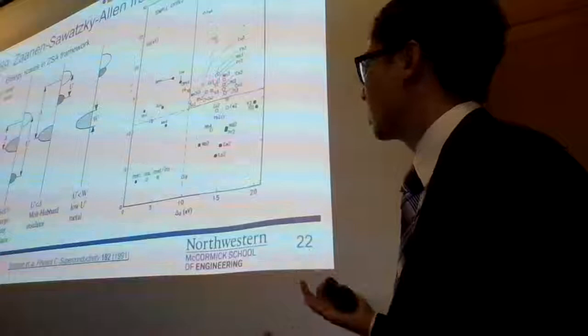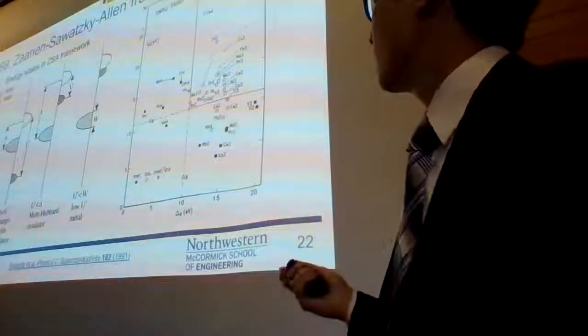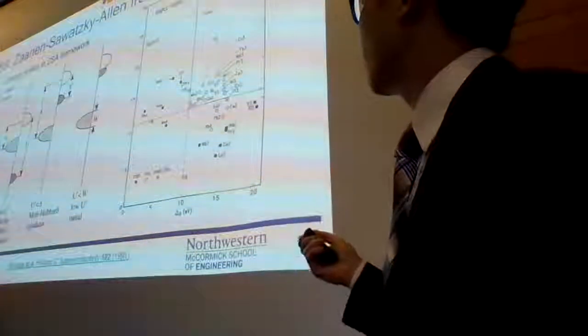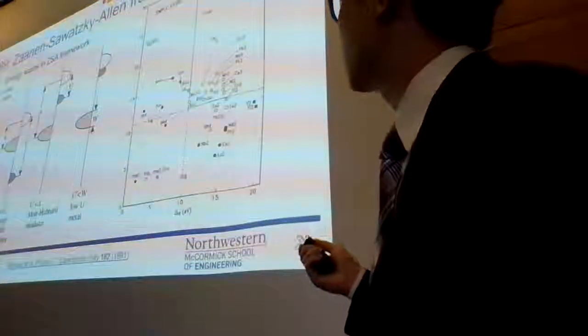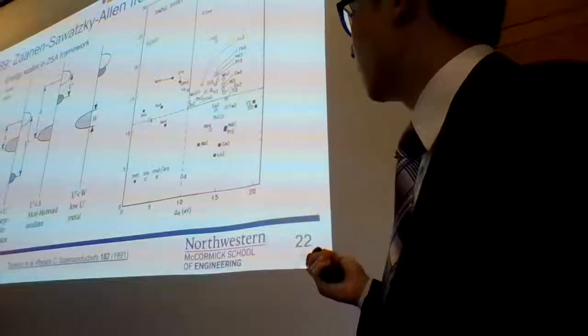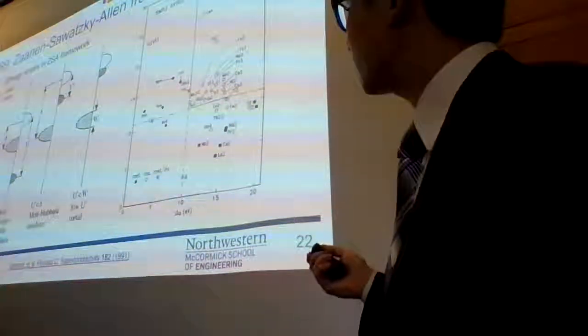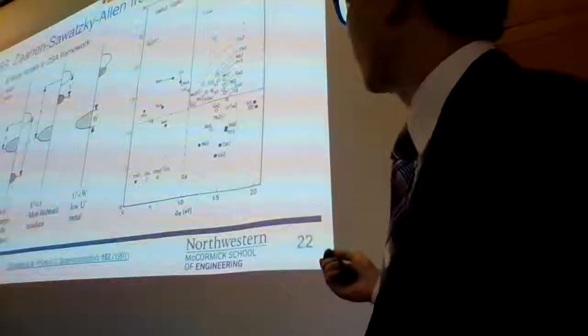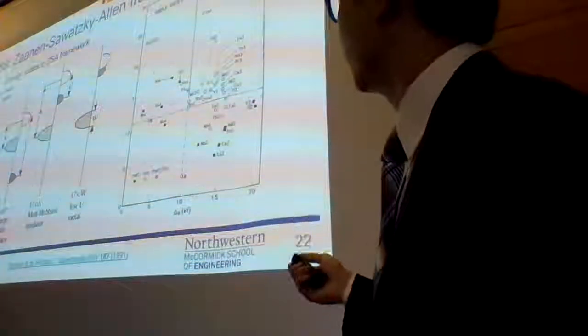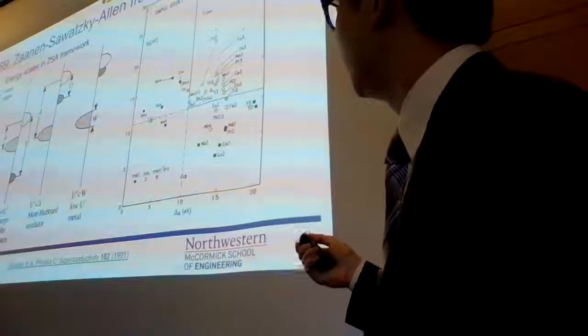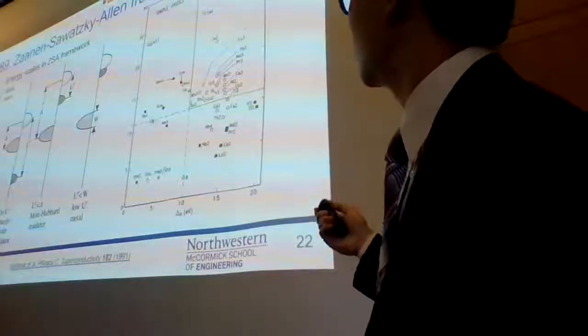It requires the structure of the material, which is kind of a downside. But they were able to achieve relatively good separation of simple oxides and some perovskite oxides at the time using just these two parameters, where these black dots are metals, which are typically clustered in the lower left, and the insulators are typically pushed up to the right.